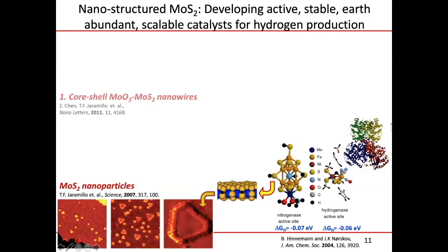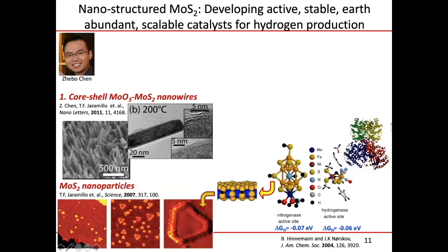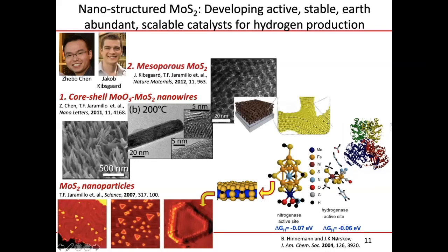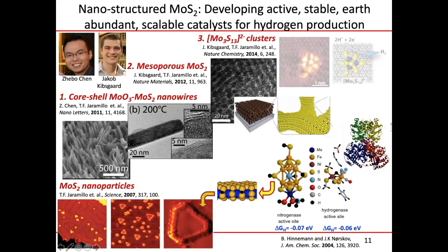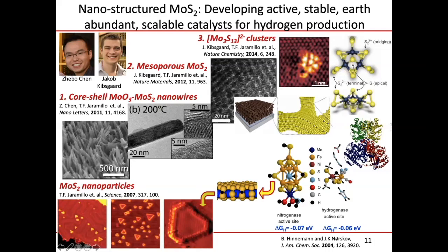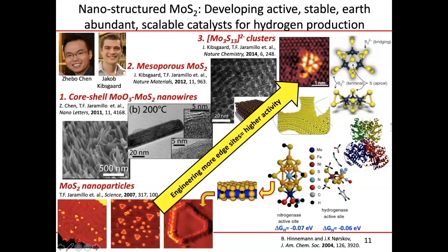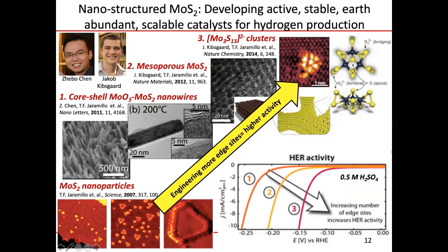And with that as a scientific foundation, coming to Stanford to start a research group, some of our early-stage researchers, Jakob Kibsgaard, went about synthesizing all kinds of different nanomorphologies of MoS2, really trying to get as many edge sites as possible to expose. And so the long and the short of it is the more edge sites you put into your electrode based on these different formulations of molybdenum sulfide, the higher activity you would get.